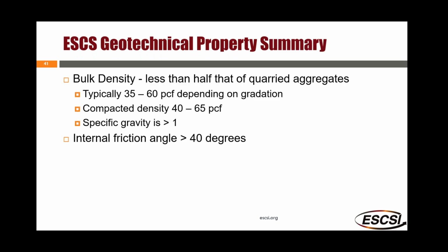Their bulk density is less than half that of quarried aggregates, typically in the 35 to 60 PCF range, depending on the grading and the manufacturer. That results in compacted densities of around 40 to 65 PCF. Its specific gravity is greater than 1, and it has excellent internal friction properties. It almost always tests greater than 40 degrees in direct shear.